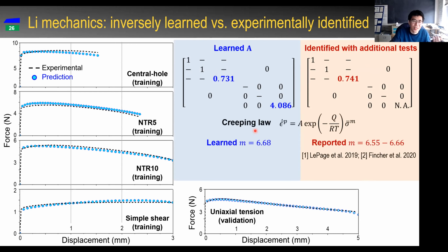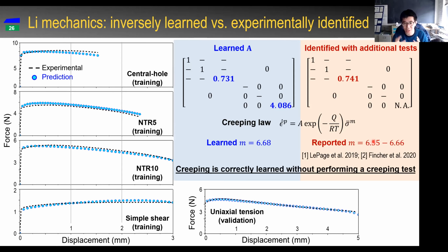More exciting is that in the simulation we put a creep law, a rate-dependent law, into the material model, and nobody did a creep test. We learned the creep parameters, and compared with what has been reported in the open literature, these two parameters are, again, very close to each other. This shows the power of inverse learning. That means creep is correctly learned without performing a traditional creep test. This is the very exciting thing about inverse learning.